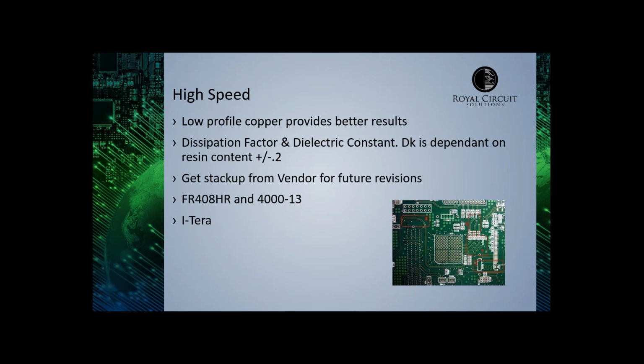If you give two different engineers the same print, we might very well build it slightly different. We'll still wind up with the layer-to-layer spacing being the same, but we might adjust the prepreg a little bit differently, use different types of prepreg to achieve that layer-to-layer spacing. So we really encourage you to ask for the stack up of how we build this board. At Royal, we'll be more than happy to supply exactly how we built it. It'll show 2 sheets of 1080 between the 2 layers.